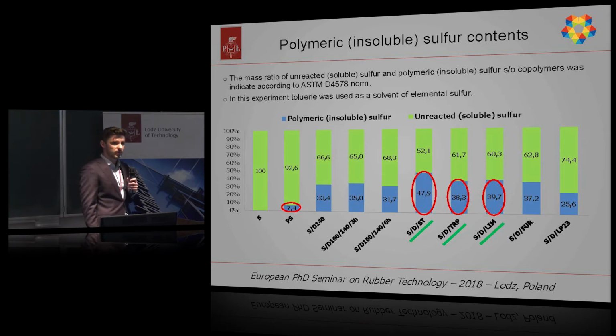As I said at the very beginning, the copolymerization product is a mixture of unreacted sulfur, otherwise soluble, and polymeric sulfur, otherwise insoluble. To purify it and indicate the mass ratio of unreacted and polymeric sulfur contents, I indicated it according to ASTM norm. And in this experiment, toluene was used as solvent of elemental sulfur.